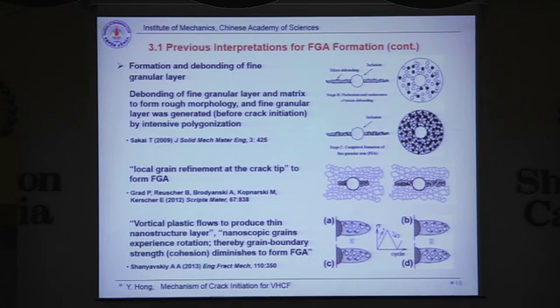And the third model is called formation and debonding of a fine granular layer. The main consideration is that during the cracking process, or before the crack growth, there will be plastic deformation that causes the formation of a fine granular layer. During the cracking process, there will be debonding between the fine granular layer and the matrix, and therefore this causes the morphology of a rough surface. There are also a couple of additional models similar to this debonding of the fine granular area to form this kind of rough surface.